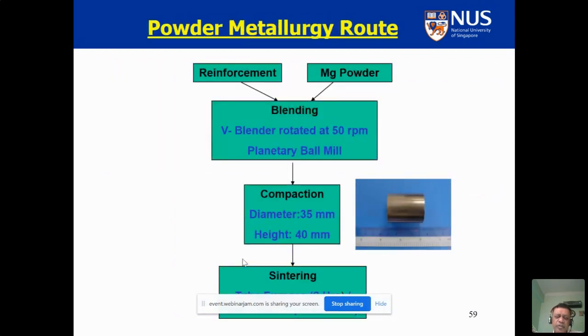We also tried the powder metallurgy route because it is another route which is widely used by industry. It's quite automated in industry. So in this case, again, we take the magnesium and the reinforcement, and we blend them so that we have a uniform mixture. You can blend it using a V blender or planetary ball mill. You can compact it after that, followed by sintering.